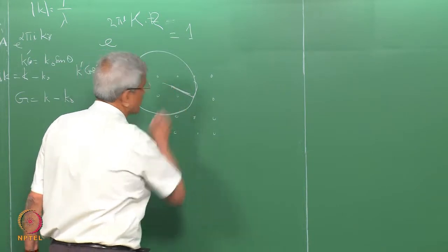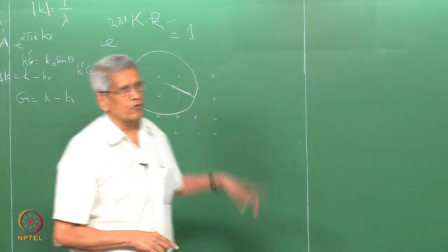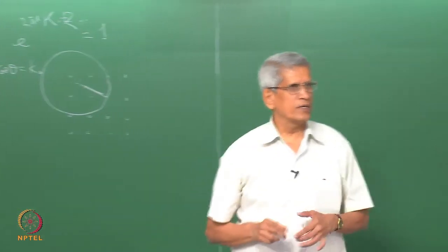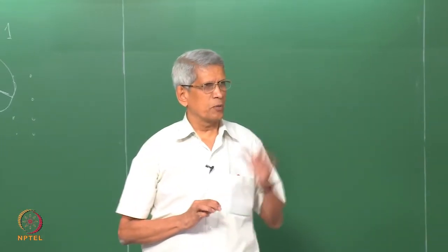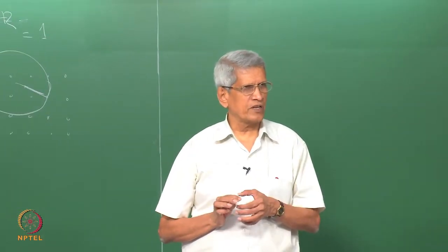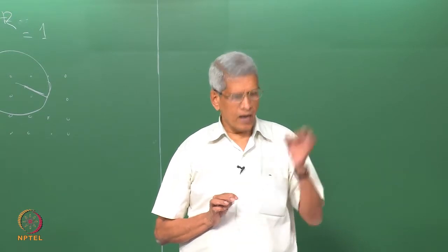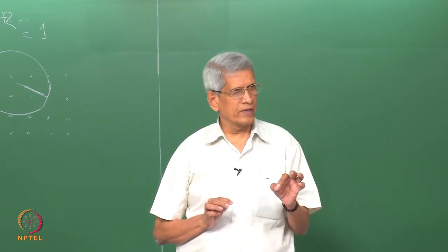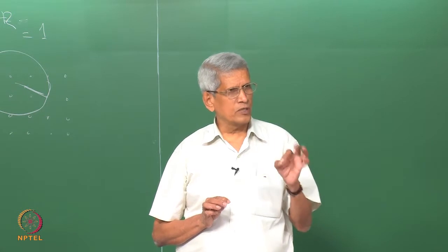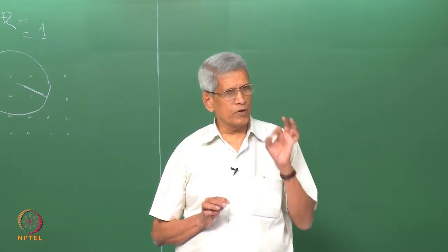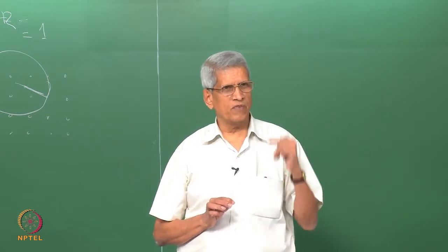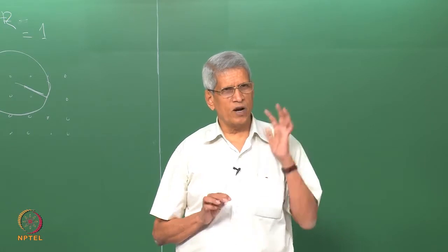So, if you draw a sphere, then try to look for what all reciprocal lattice points are lying on the surface of this sphere. All these points are the ones which will give rise to diffraction for the specific direction in which the beam is falling onto the sample.